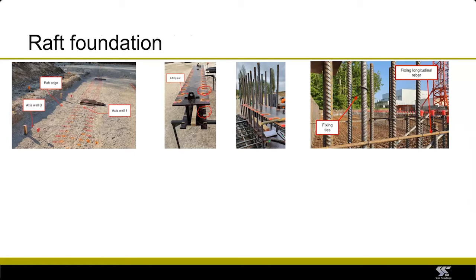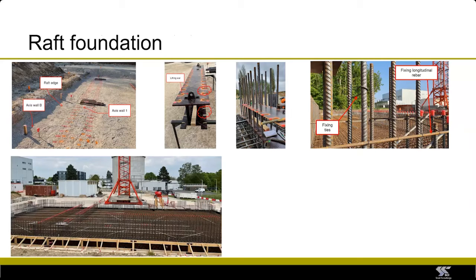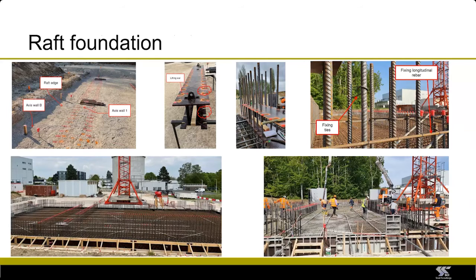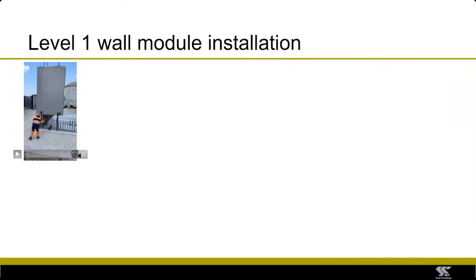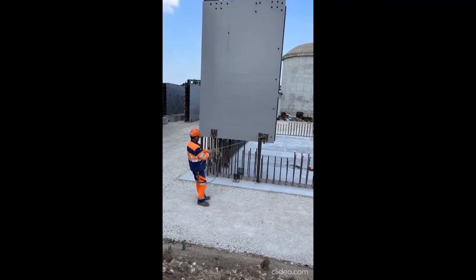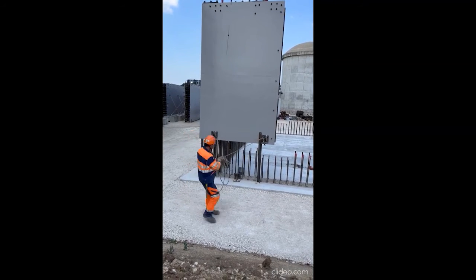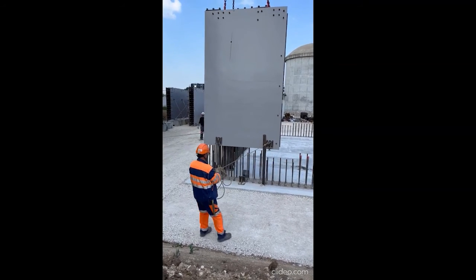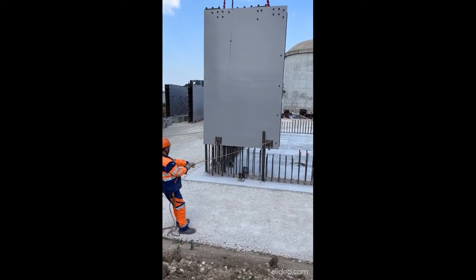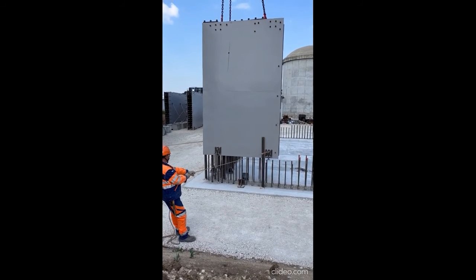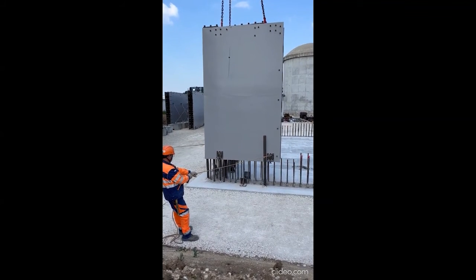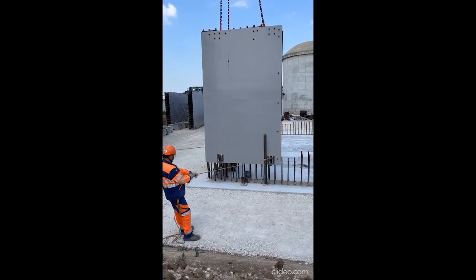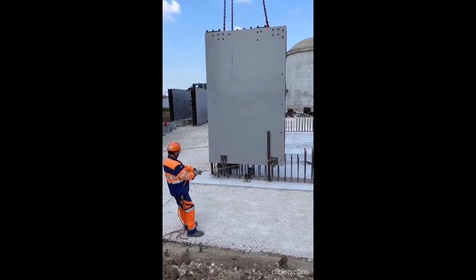And once the starter bars were installed, they were then tied in position in 2 directions to ensure that they did not move during concreting. Then the reinforcement for the raft was completed and concreted. And here you can see the installation of the first module being lowered by the tower crane, guided by 2 guys with ropes so they can do the guiding from a distance without getting too close to the module being installed.